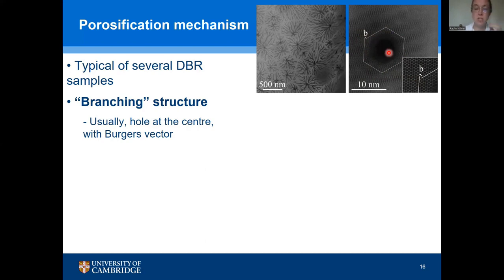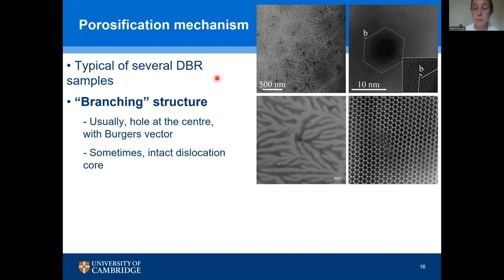So the defects have actually turned into pipes through which the etchant can run. Sometimes we can just about still see the atomic structure of the defect. So here we've got one of these holes from which the pores seem to emanate, but rather than there being a completely through-the-sample hole, there's actually just a thin layer of material left. And then we can see where the bonding is wrong down this line of defect in the crystal in this atomic resolution image. And we can identify the crystallographic nature of the defect.